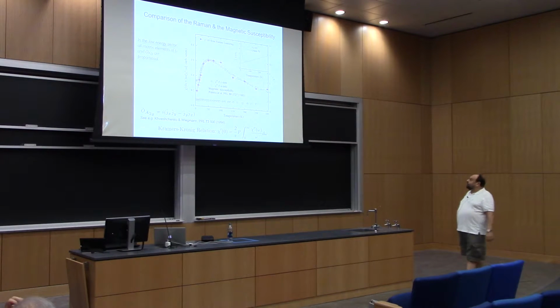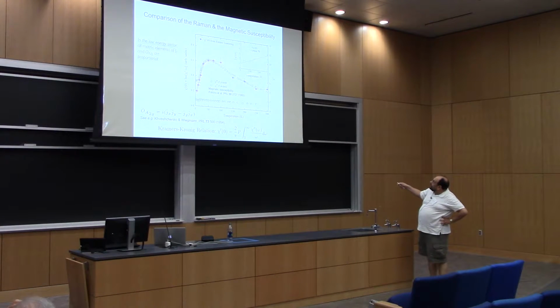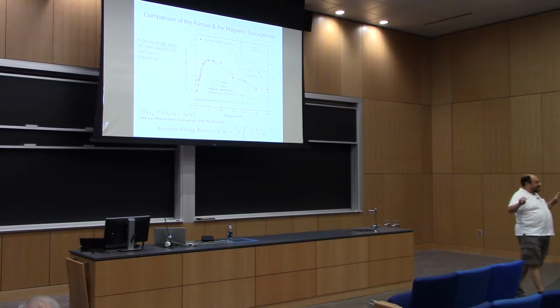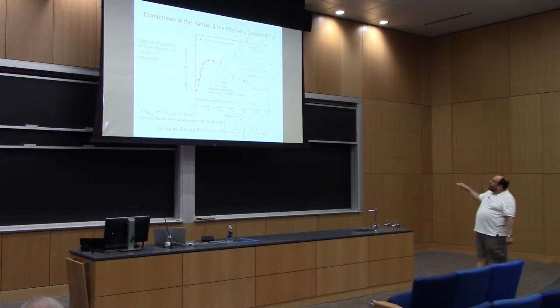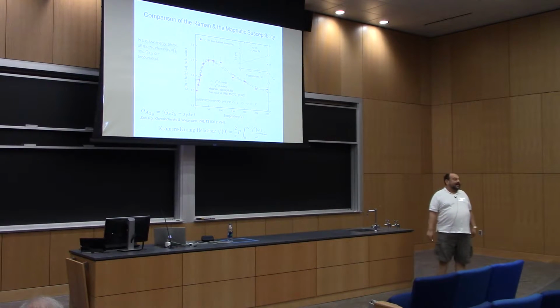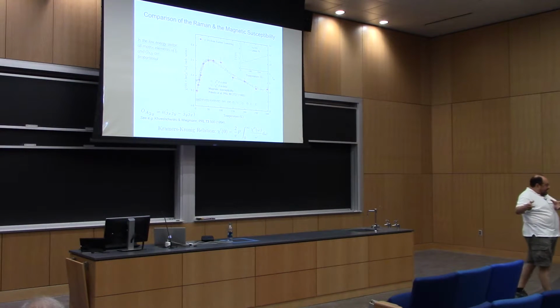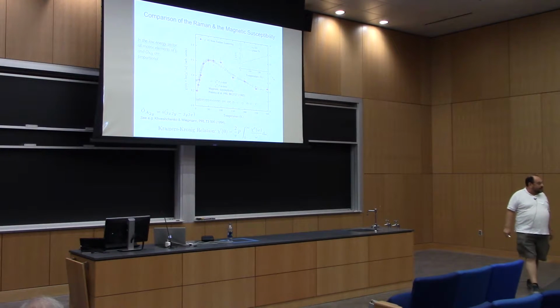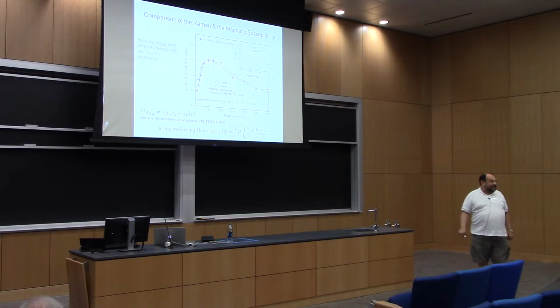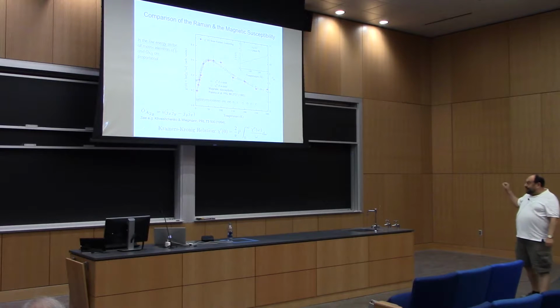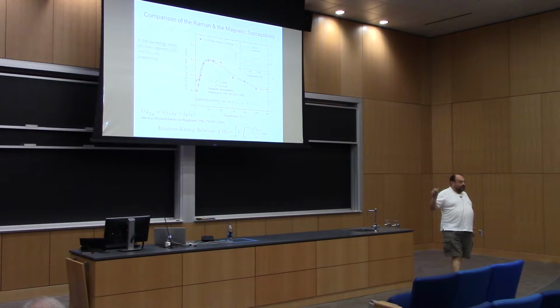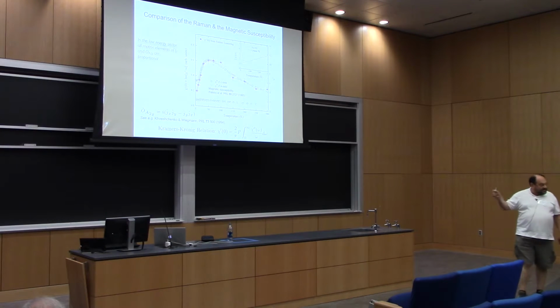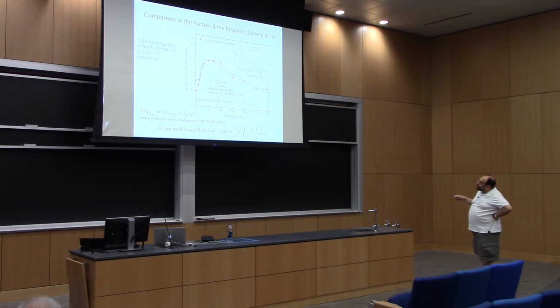It's a staggered phase. So in my opinion, what happens here, there's a beautiful Curie-Weiss temperature dependence at high temperatures, and this is where the system locally fluctuates and doesn't really establish staggered order yet. But at this turn up in 1 over chi, or turn down in chi, it actually starts building correlation lengths at 100. That's where the neutrons see the collective mode, and that's where the hidden order Bragg peak has to appear. So this Bragg peak has not been accepted. And that's again the issue of doing the experiment the right way, because it's not magnetic and neutrons can't see that. But this is the fluctuations towards the Bragg peak, and this is where the system decides that it's actually a staggered order, not a uniform order that is being built up.